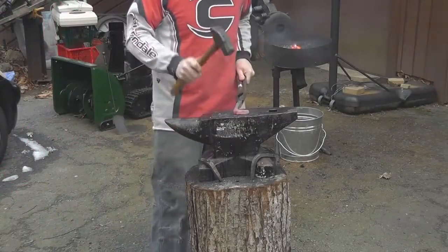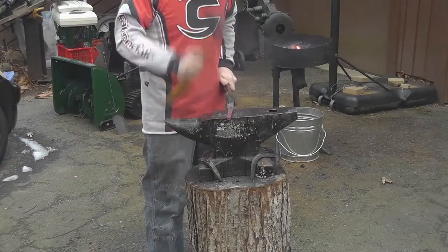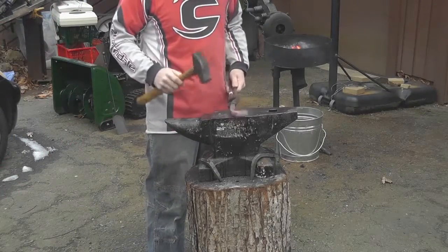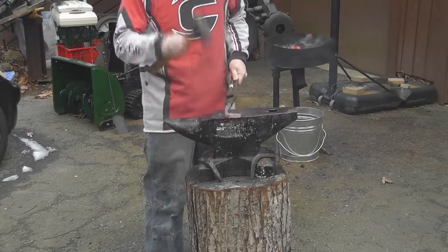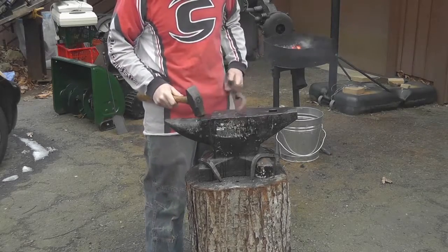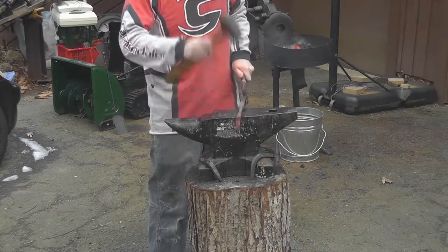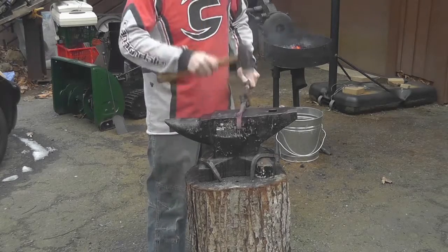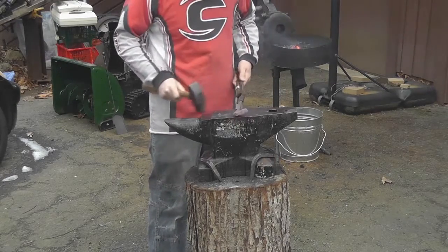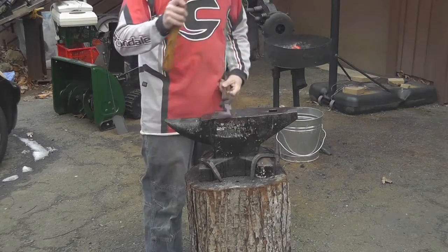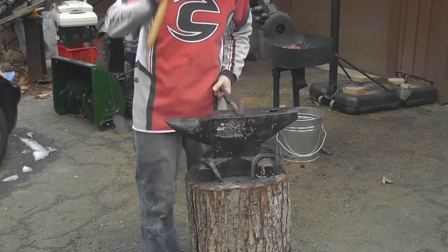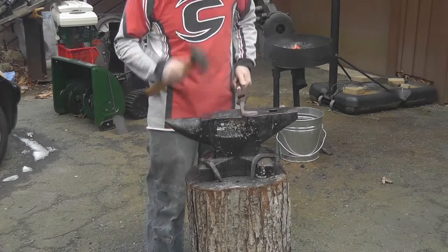The blade was hand-forged using a charcoal furnace for heat. In order to create a blade with functional hardness, the steel was heated up to a critical temperature of 800 degrees Celsius and then quenched into oil. The blade was tempered at 175 degrees Celsius to decrease the brittleness and gain a straw color, and then at 350 degrees Celsius with a propane torch for the blue color.